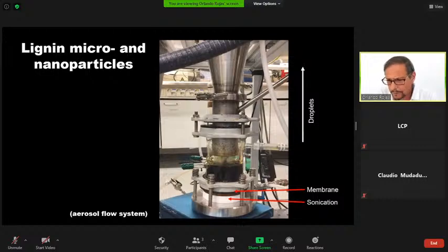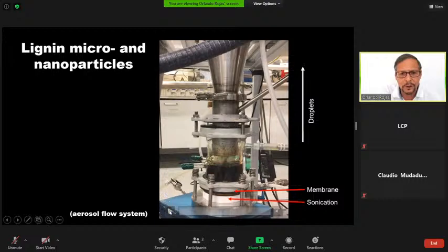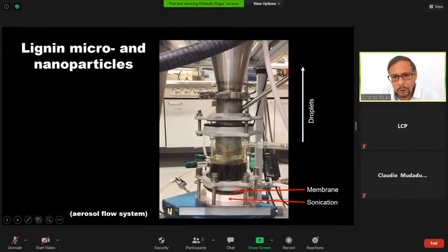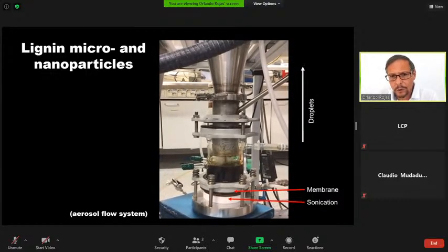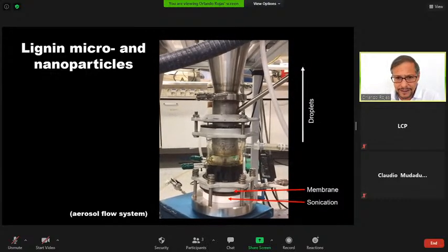So the production of lignin particles using solvent shifting or anti-solvent methods has been known since several years ago. But in those methods, usually you obtain lignin particles that are going to be dispersed in a liquid medium. What is different here is that we have a system where we use an aerosol flow reactor to atomize black liquors or lignin solutions that are carried by a gas carrier. And by using a sonication or a vibrating membrane, we produce liquid droplets that are carried up in the heated tube that you see on top.